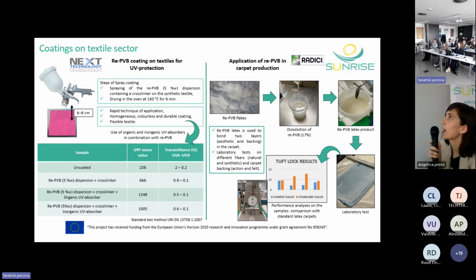Next Technology Textile is working in application of this recycled PVB as coatings on textiles for ultraviolet protection. So they have used this material in solution and in dispersion, containing crosslinker for increasing the adhesion to the textile. And by spraying and drying method, they have applied it on textiles. And they have obtained good results in terms of homogeneous, colorless, and durable coating, also maintaining the flexibility of the textile. And they have also incorporated UV absorbers for making this functionality, this additional protection to the coating.